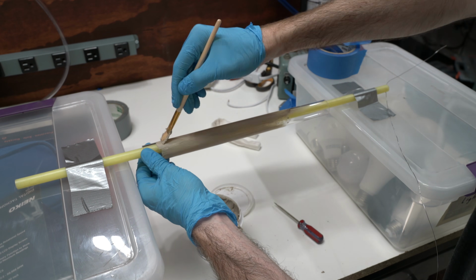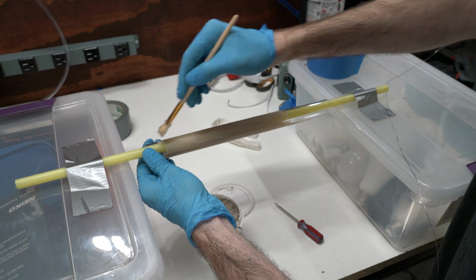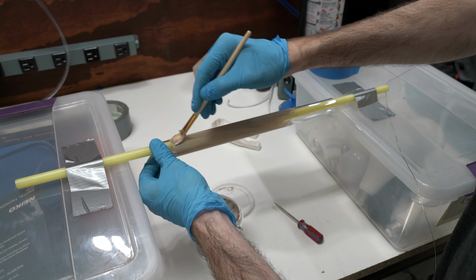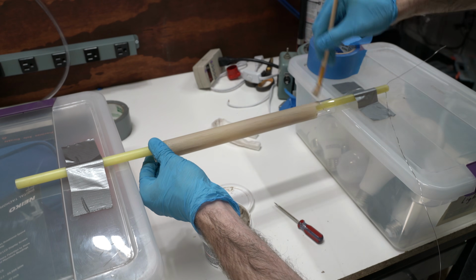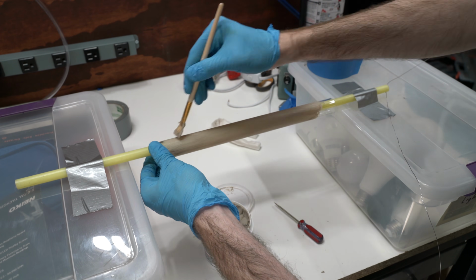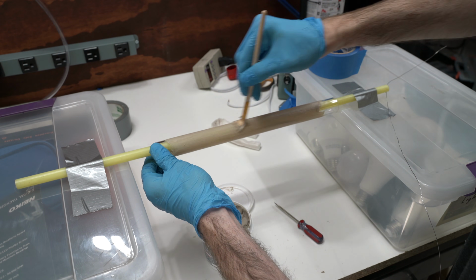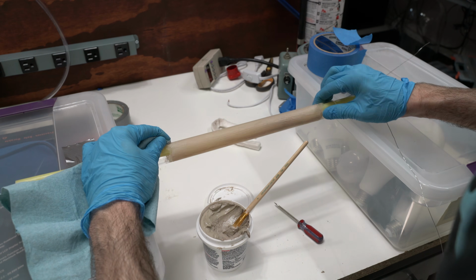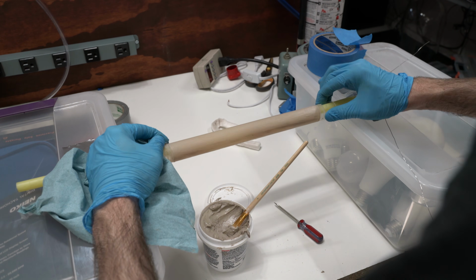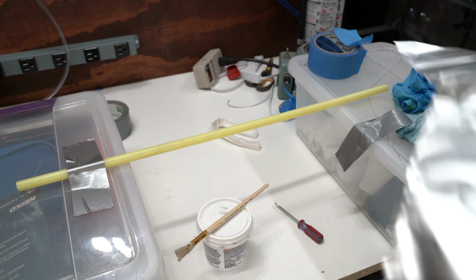I discovered this when my first tube developed radial cracks exactly where the nichrome wire was touching it. It's also possible that these were caused by thermal stresses, but at any rate, when I started applying this layer, the problem cleared up immediately. Now I'm using a paper towel to clean up some of the cement on the ends of the tube. Now I'm putting the tube into an oven at a relatively low temperature of 100 Celsius.